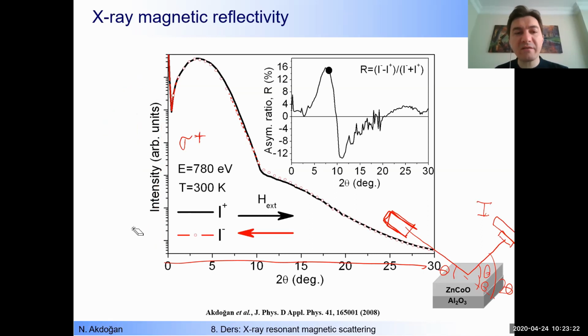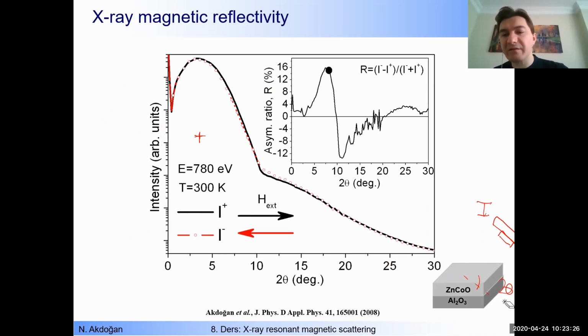But then what is I plus? What is I minus? So for the first measurement, which is shown by the black color here, I apply magnetic field in that direction, and then I measure the reflectivity curve. I measure the intensity plus at the detector. Then I reverse the direction of the magnetic field. I apply magnetic field in that direction, and I am repeating the reflectivity curve here again. So I record the intensity at the detector. Now I call that intensity under reversed magnetic field I minus. Okay, so I minus and I plus are the intensities recorded for different directions of the magnetic field applied parallel to the sample plane.